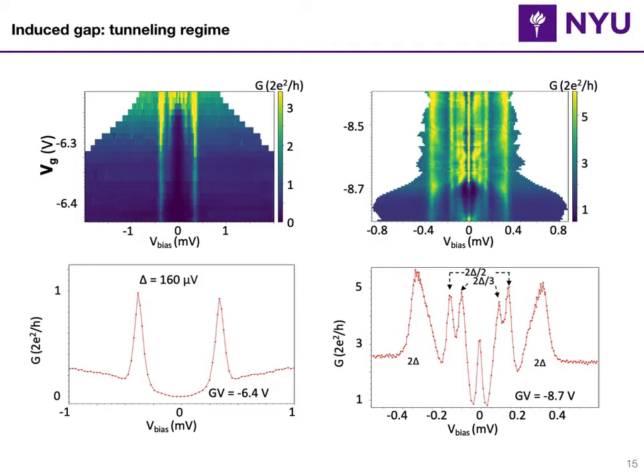So first of all, to make sure that the induced gap is actually good in our devices, we do a quick characterization on voltage biased Josephson junctions. As you see here, we have a relatively hard gap. In this one, the induced gap is about 160 microvolts. And we can also resolve multiple Andreev reflection peaks: 2 delta, 2 delta divided by 2, 2 delta divided by 3. That shows that the quality of the interface is quite good.